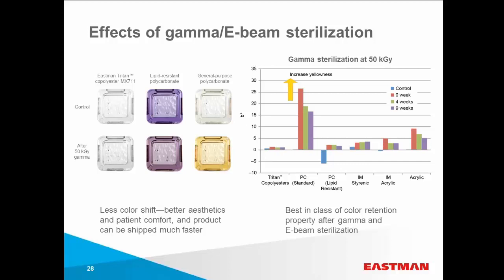In the case of the copolyester, in this case the Tritan family, you see very minimal color shift after sterilization, and it recovers very quickly to close to the natural that you just molded. So that means you have a product now that you can control. If you have a device that you need to have in a transparent or opaque color, it will now maintain that color after sterilization, where before you were having to live with a shift in color. Next slide, please.